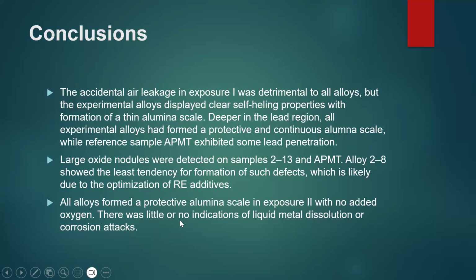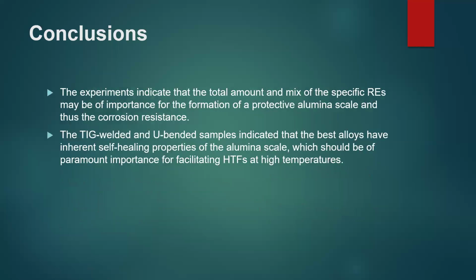There was little or no indication of liquid metal dissolution or corrosion attacks. The experiments indicate that the total amount and mix of specific reactive elements may be important for the formation of protective alumina scale and thus corrosion resistance.